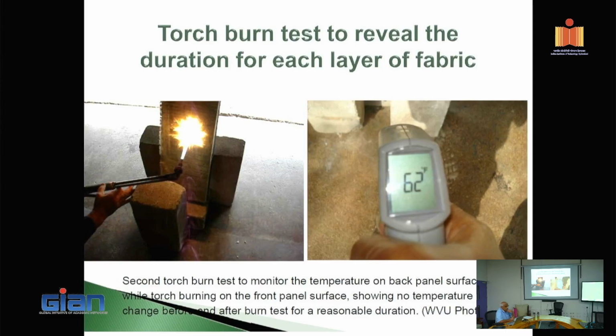Another thing, I have a different core material than balsa wood. In this case, this is a carbon foam. The message here is, the torch is about 2200. After about 4, 5, 10 minutes, that's my IRT, infrared thermography. The other side is still 62 degrees. You can keep your hand on there. This is after half an hour or whatever, back side of the panel. So the thermal resistivity can be controlled depending upon the foam that you're using. Of course, we use a carbon foam for some other reasons. Never mind, whatever the reason, if you use the right kind of core material, you can get that.